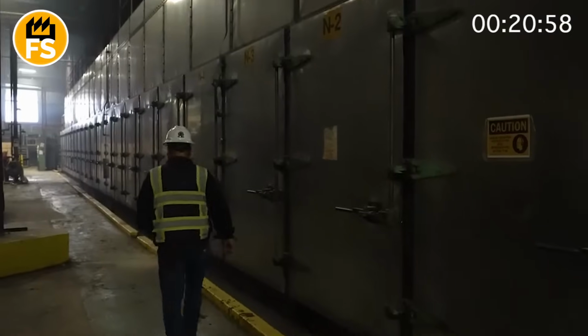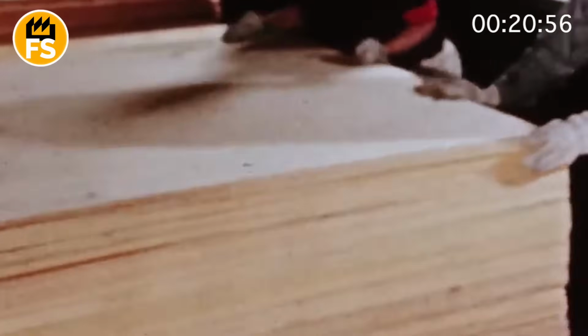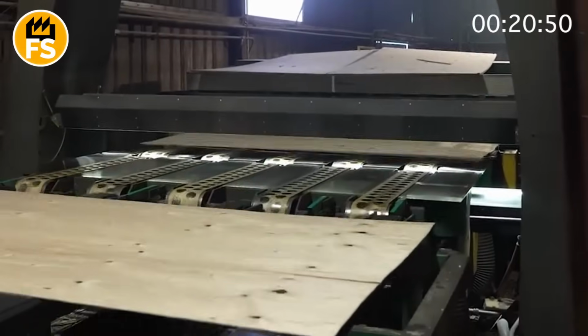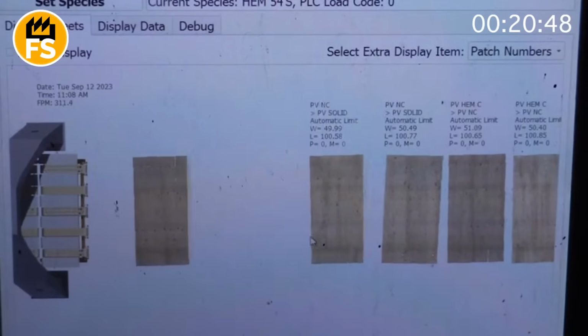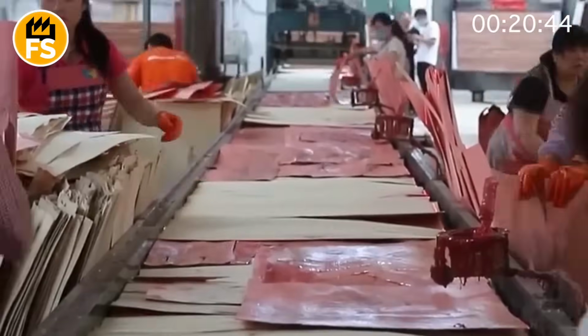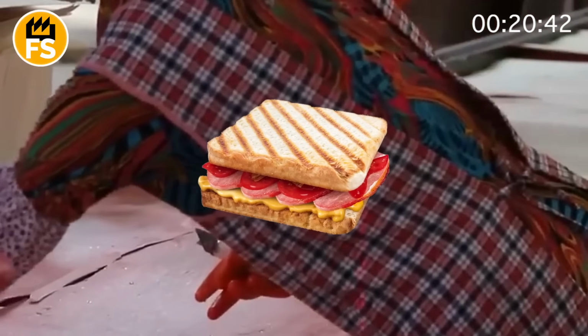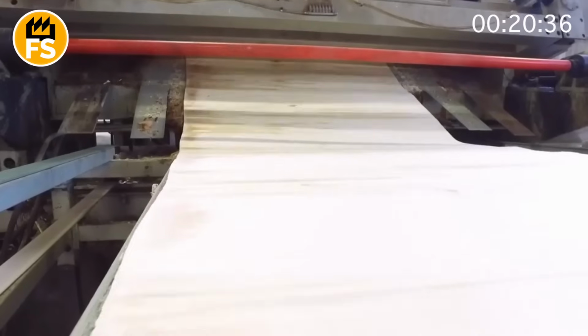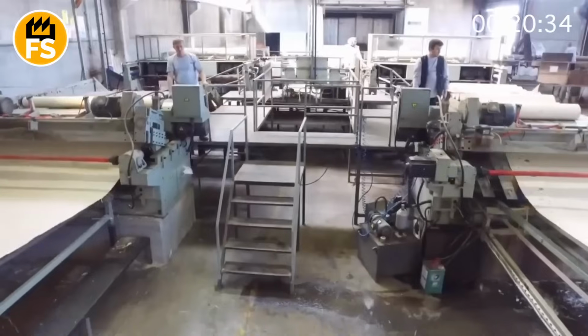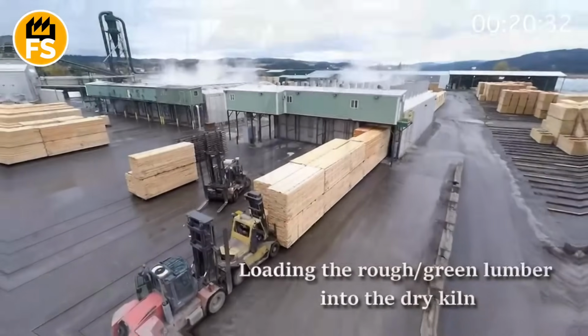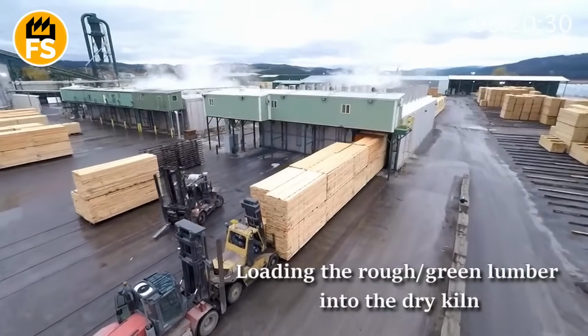Because plywood isn't just glued sheets, it's cross-laminated layers, where each layer runs perpendicular to the previous one. This is how it gets its mechanical strength, flexibility, and resistance to warping, like a bulletproof vest, but made of wood. The finished sandwiches of several layers are placed in a giant hydraulic press that applies pressure from 150 to 250 psi, at a temperature of about 300 degrees Fahrenheit.